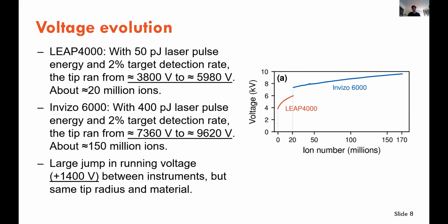So now I'll walk through some of the running parameters from the LEAP 4000 and the Invizo to compare them. Some of you might find this interesting from actually running microscopes on your own. So 50 picojoule laser pulse, the LEAP 4000's voltage profile looks like this. There's then a large jump in running voltage when you transfer it to the Invizo, and then it runs really, really smoothly. When we first received the Invizo, we were surprised to learn that it runs at such high running voltages, but chips run really, really well at high voltages, and such a jump is actually normal and expected.